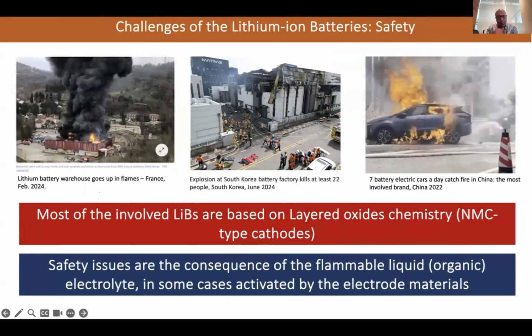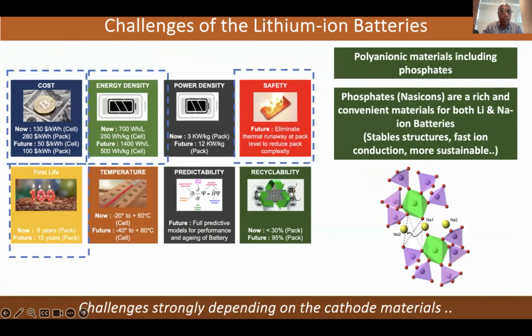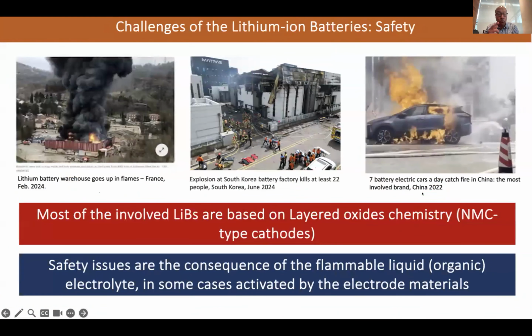So let's go for safety. Here are some pictures from some recent problems that occurred in France, South Korea or China. Sometimes there is spontaneous burning of the battery, but sometimes there is some abuse of the battery. But when looking at the chemistry inside these batteries, we see that we have only NMC, and NMC is an oxide. A battery is a closed space, a closed engine, and to have this combustion we need oxygen, and oxygen in general comes from the oxide, from the cathode material. That's why polyanionic materials like phosphate are much safer, because the oxygen is more strongly linked to phosphorus to form this PO4 unit. The PO4 unit is very stable, and oxygen cannot be released from the structure to induce this flammability or safety issue.